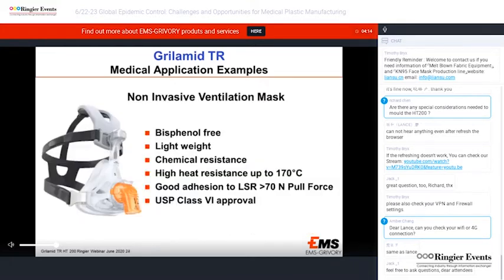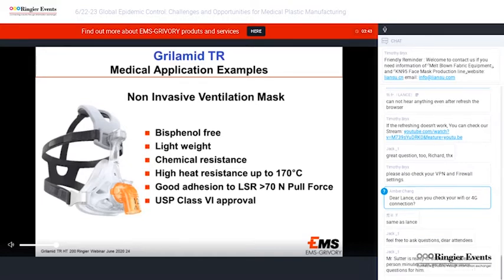This application for a non-invasive breathing mask takes full advantage of all the benefits of Grilamid TR, like bisphenol-free, lightweight, chemical resistance, high heat resistance up to 170 degrees, especially suitable for silicone overmolding, allowing the curing time to be reduced, as well as good adhesion to silicone with a pull force of over 70 newtons. And last but not least, the USP Class 6 approval. As you can imagine, this application has ramped up considerably over the last 6 months with the spread of COVID-19.